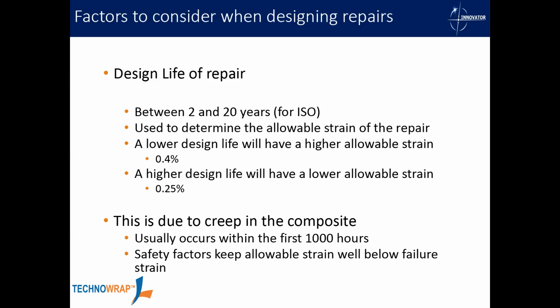What happens is, unlike a steel, the composite actually degrades as a function of load and time. We're not talking low loads here; if you're holding it at pretty much ultimate failure strain, ultimate failure stress, that you would see the composite begin to creep. So the allowable strain actually decreases as a function of the load it's seen and the time it's been applied for. So to relate that back into a pipe, we may be able to offer a very long design life on a repair that's fairly low pressure, but if that pressure starts creeping up, say on that 12-inch pipe, the 250 bar, maybe if that was at 300 bar, you probably wouldn't be able to see a 20-year design life. You may need to decrease the design life to allow the various strains and the calculations to work.